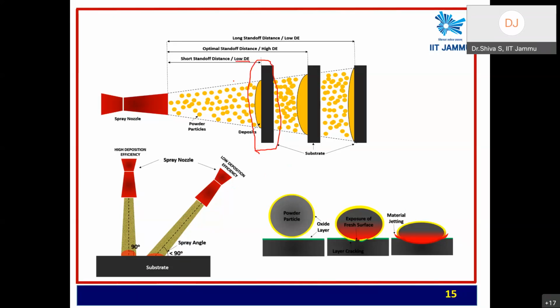Why is that happening? Because a tremendous amount of speed is hitting the surface, and as these powders are highly charged and have a high kinetic velocity, at times the powder particles, if they are very large, if they are not optimized between 10 to 50 microns, anything more than that, will hit the surface, and two things can happen. Either they just hit the surface and revert back, so proper first-layer impingement does not take place so easily, or the powder particles themselves start breaking. And if the powder particles start breaking, eventually you cannot expect the material property that you would like to have.